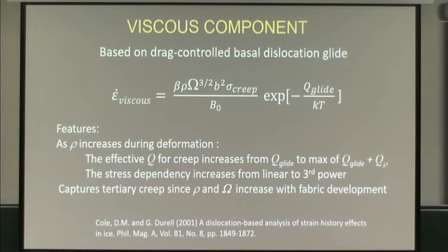So how do we model that? Well, it uses the same mechanism. I won't get into the details hugely, but the viscous strain rate is linearly a function of the dislocation density. You'd say, all right, great, that's easy, linear law. The thing is, we already saw that rho here is a second power function of stress. So when stress is high enough to produce a lot of dislocations, this gives you a third power law. When it doesn't produce, it's just drifting around existing ones, it's a linear law. As we'll see in the application in a minute here, that's pretty handy because we aren't living with a third power stress relationship with a bunch of linear terms. They're all linear until you start producing dislocations, okay?